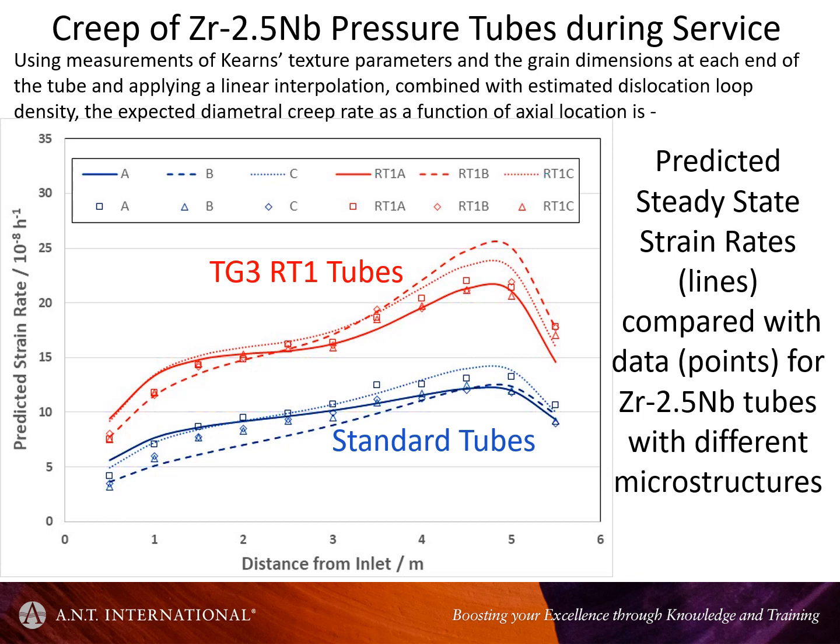And we can measure the microstructure with X-ray diffraction. When one inputs the microstructure from the radiation damage, combines that with the microstructure from the dislocations, the microstructure from the grain boundary sinks, if one throws everything into the pot, so to speak, creates your damage, and then decides where everything is diffusing, which was simply balancing the mass transport, one can then model the creep of the pressure tube.